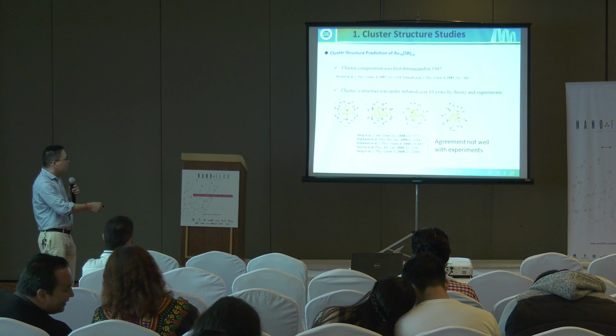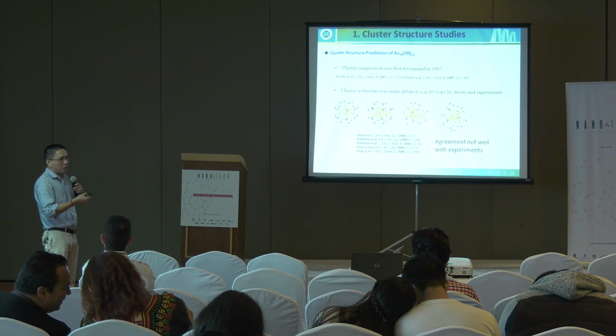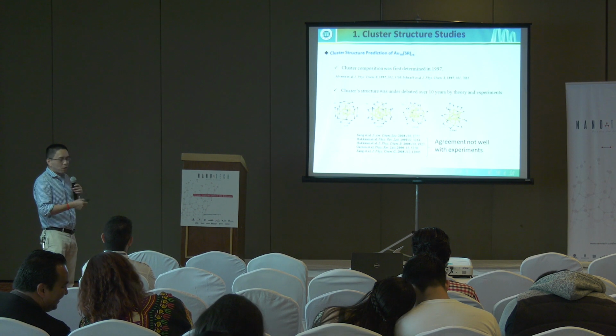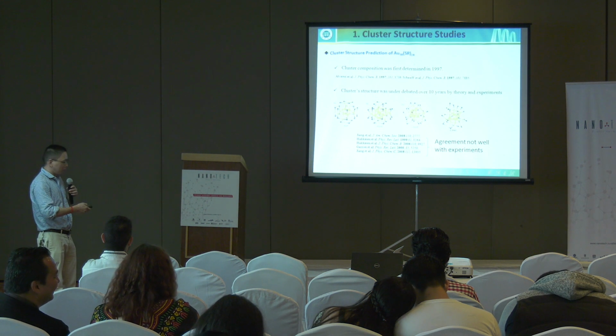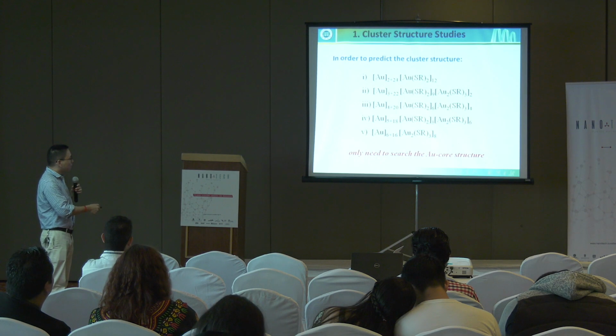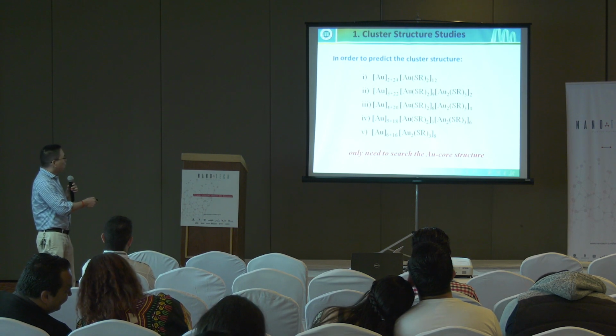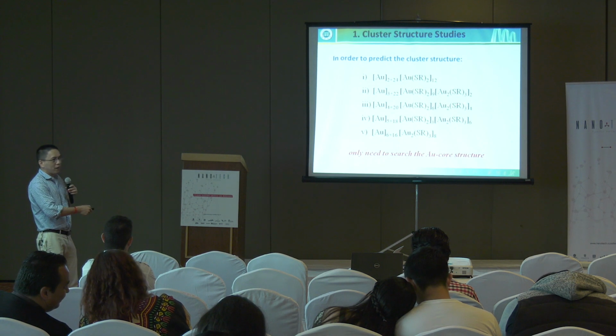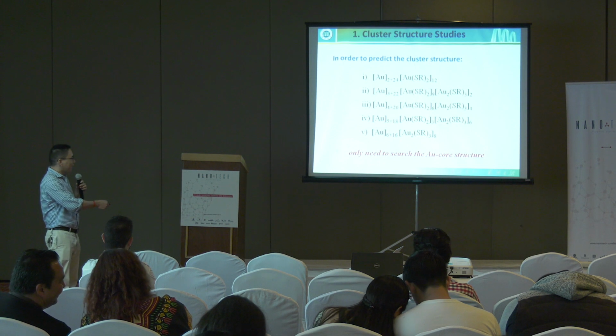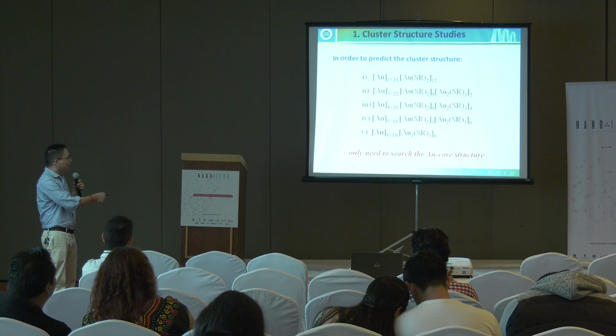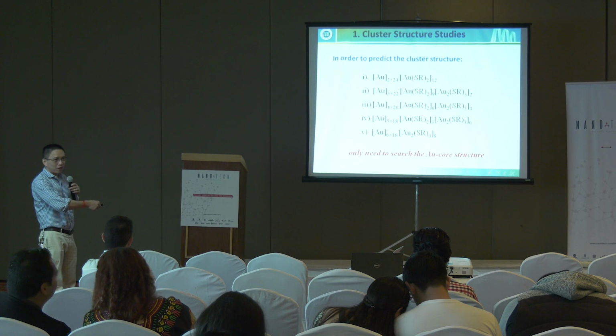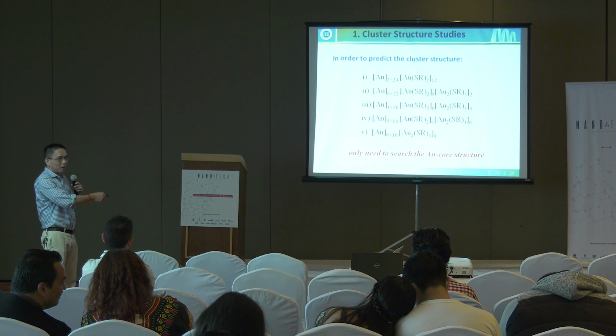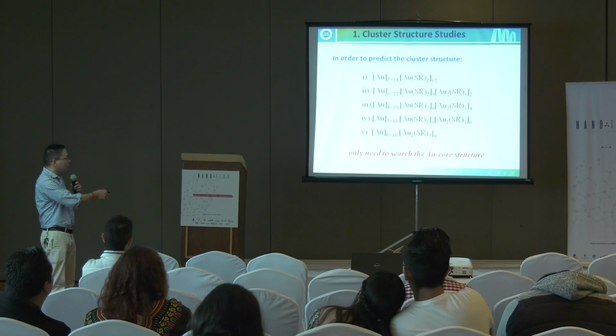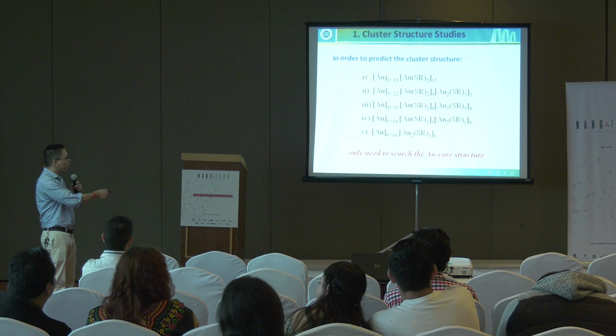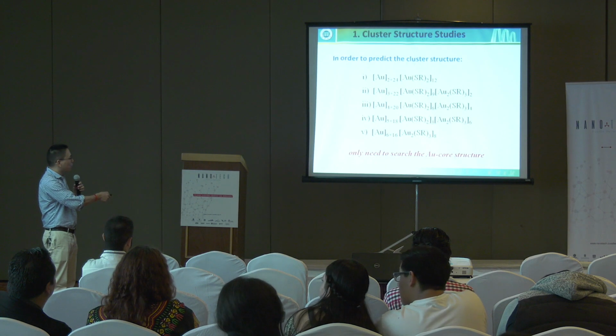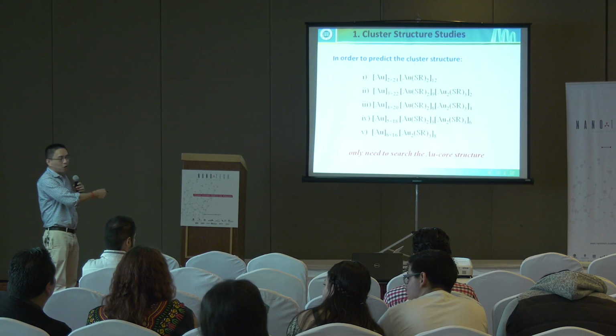However, all these structure models obtained from theoretical methods do not agree very well with experimental measurement. So with our proposed method, we can predict the structure in a simple way. We first divide the cluster into metal core and ligand shell. We find that there are only 5 possible formulas for gold 38, so it can only have 5 types of gold cores. So what we need to do is to search the structure of the 5 gold cores.